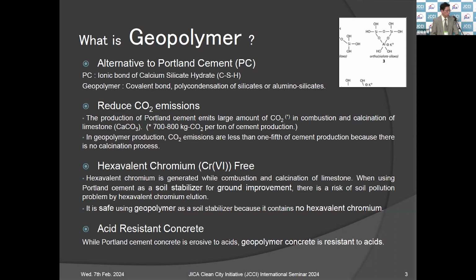And in the case of Portland cement, in its calcination, the raw material contains chromium. It's a metal. And normally it's oxidized and it's harmless, but when you calcinate it at above 1000 degrees, it generates hexavalent chromium, which is harmful. But the geopolymer does not contain hexavalent chromium out of the calcination process.